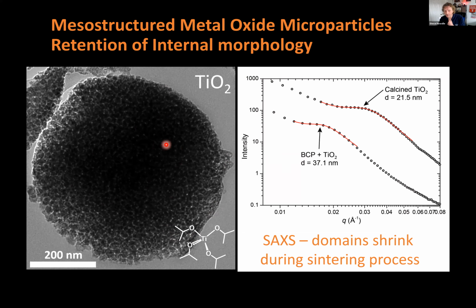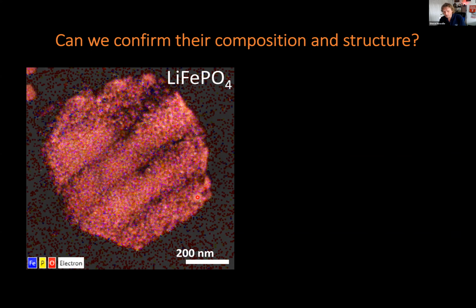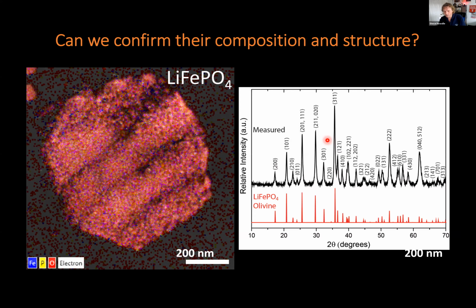We did this not only for titania, but also for lithium iron phosphate, another material that could be used in battery applications. We confirmed their composition and structure using EDAX, looking at the X-rays kicked out in electron microscopy, and we can show that we very definitely have the anatase structure of titanium dioxide. Similarly for the lithium iron phosphate, we've got very similar behavior, and we can show that we're getting the right olivine type structure when we look at the crystal structure of these materials.